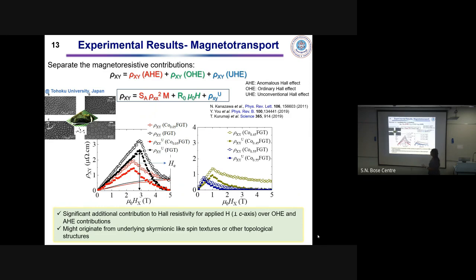Now, when this magnetic field was rotated and applied in the plane of this crystal, all these stripe-like domains merge together and form lattice-like structures, even for a small magnetic field of 20 millitesla, because that's the magnetic field we could access over there. We could see that they form lattice kind of structures, and that was present in the doped compounds also. Can you see the pattern even on FGT with 20 millitesla? Yes. But then here, if I see, the critical field is very high. Yes, that's a question that we also have, and that's why I'll tell you, because we didn't.